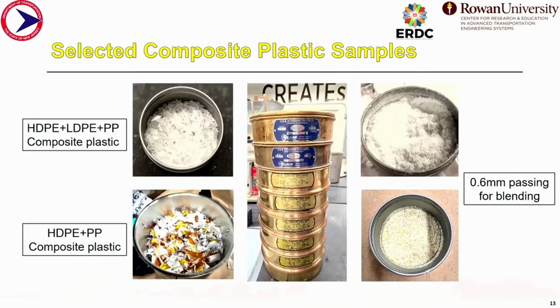So we chose two types of mixed plastic here. One of them is a mix of HDPE, high density polyethylene, LDPE, low density polyethylene, and PP, polypropylene. Another one is the mix of HDPE plus PP. After grinding and sieving, we get 0.6 mm passing for blending, because the size and the blending time and everything were chosen based on an optimization process. After the whole process, we came up with this size for the blending.